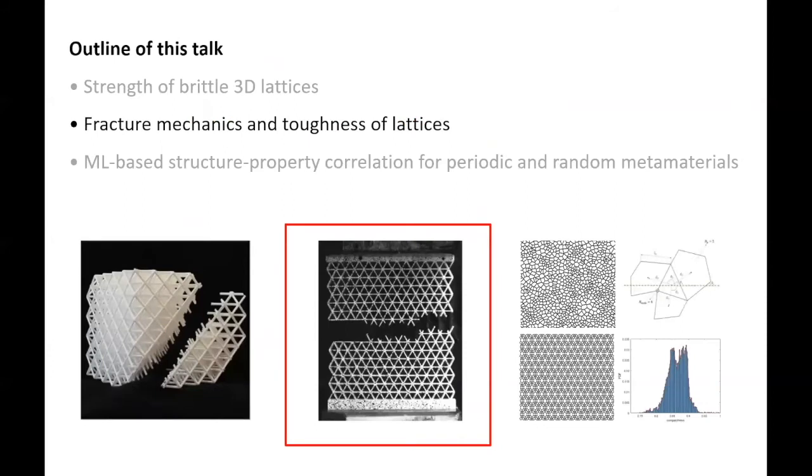Can I ask you before you move on to propagation? If I understood correctly, you're saying that the problem is the junctions. Everything breaks at the junctions, is that right? Right, so one problem is the junctions. Sure, the problem is the beams, but it's breaking at the junction. It's very complicated, because in some of them it would be directly at the junction, and some of them would be right outside, which means that if it's right outside the junction, the beam can capture that.